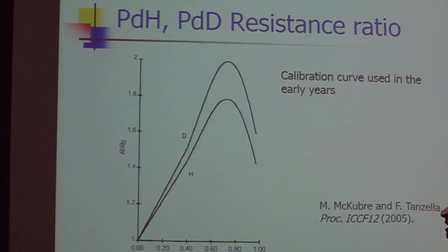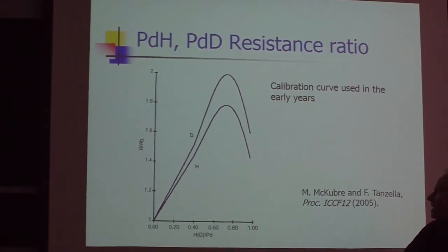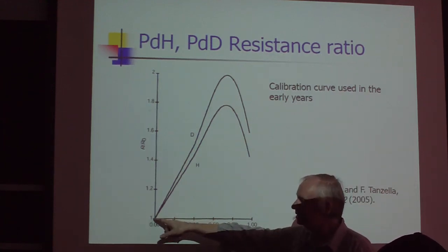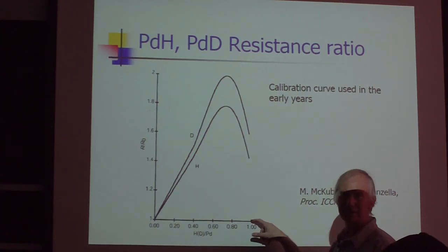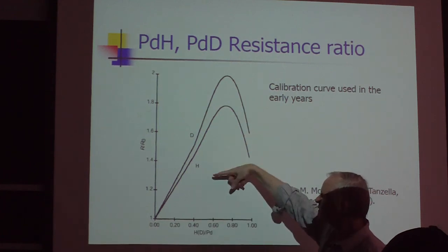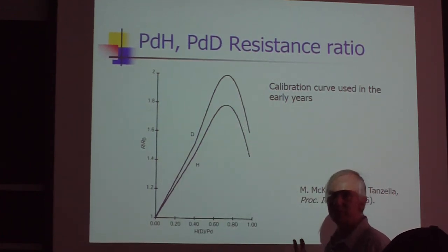So it's been known since at least the late 1920s, 1930s, if you have an ordered metal, you can compare it with an alloy metal—disorder associated with an alloy causes an increase in resistance. Your typical alloying curves will have a peak where you've got half substitution. So here you get the same kind of thing. If you think about palladium, here's ordered palladium, while hydrogen and deuterium in the octahedral sites causes disorder. So disorder in the middle gives a peak in the resistance.